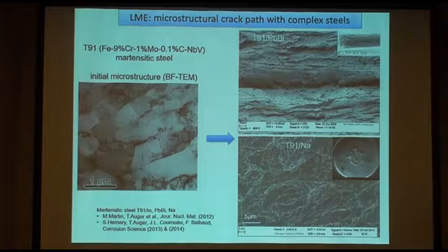And when we tested this material with different liquid metals, so for applications we tried eutectic lead bismuth, we encountered very specific fracture surfaces, such as this one. The crack front ran actually horizontally in this sample.